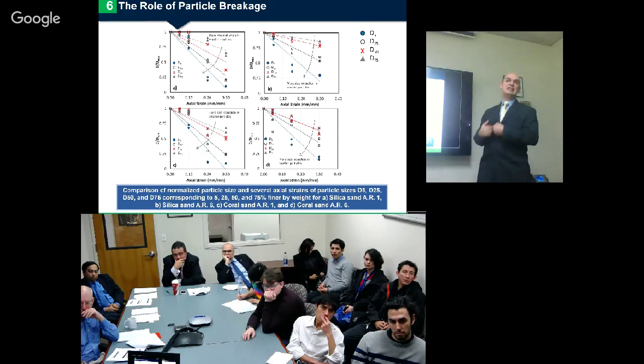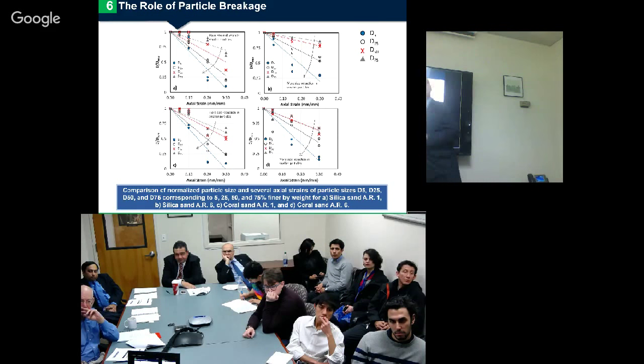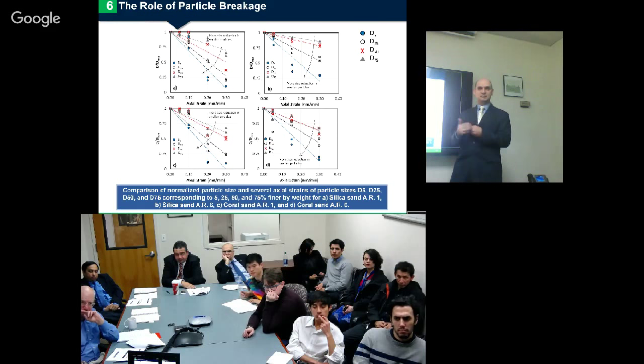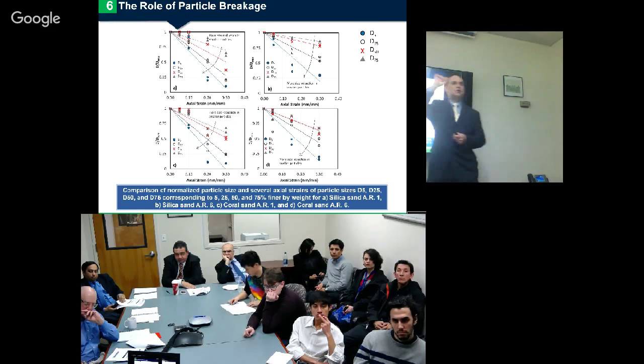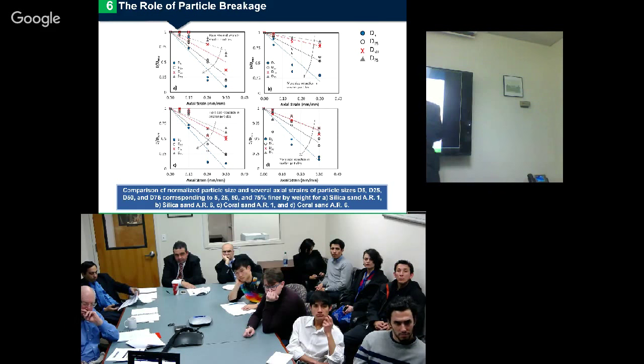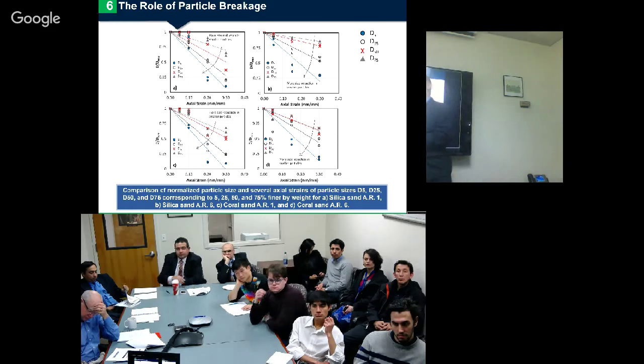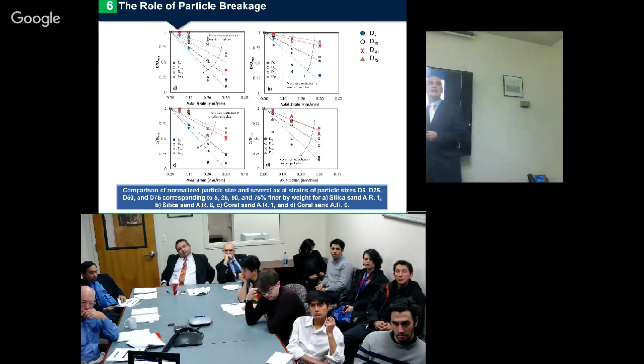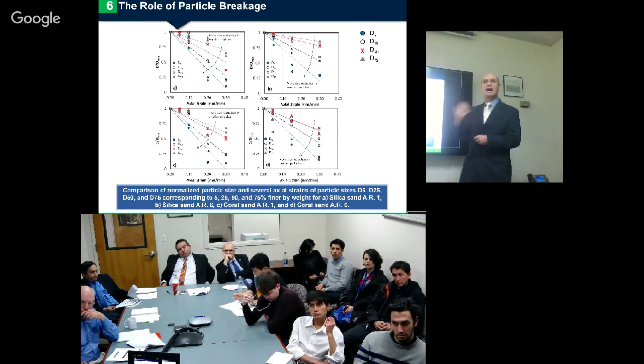Now, what I did here was I normalized the diameters: existing diameters divided by their own maximum diameter. In other words, if we have zero actual strain, it is the original material. That's why every single line starts at the origin, which is 1. Now, after the sample is loaded at different axial strains, 5, 10, 20, and 30, we can see that this normalized factor is being reduced. What reduces more, the larger or the smaller particle? I thought initially that the larger particle was going to break more.